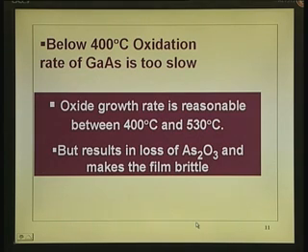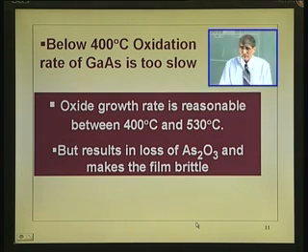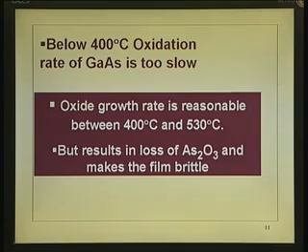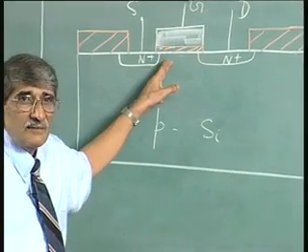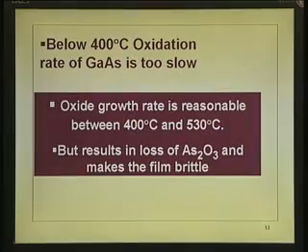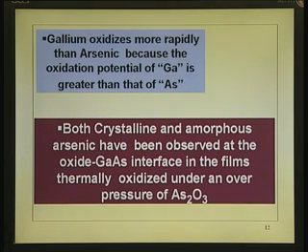If they are brittle, there may be pores around because of cracking, and when there are cracks all around, if you put a metal on a crack in the oxide, it is a short circuit. So, this is one of the problems that you have in hand. Now, people try to overcome that problem.